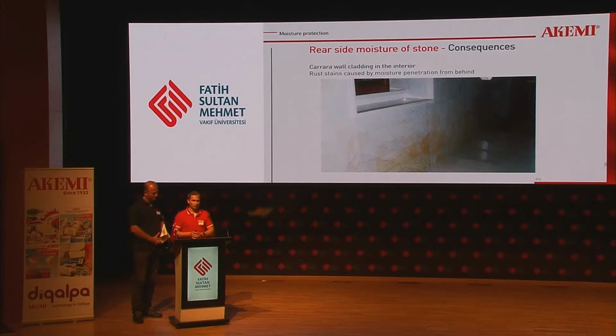So if you use such sensitive stones, it's really hard when you don't protect them from the backside, because the moisture comes inside, it will rust the whole stone, and you will never be able to restore it, even with grinding, because it comes from the inside.